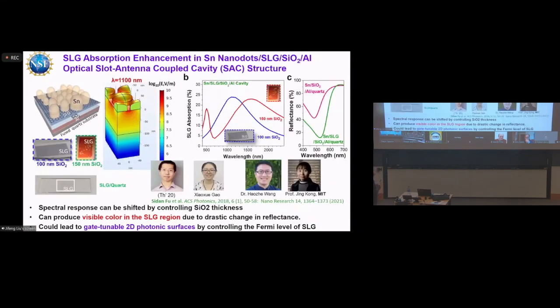So what we did is that we put the graphene essentially on a dielectric cavity, so aluminum mirror on the bottom, dielectric layer, graphene, and then we deposited some self-assembled nano dots with very narrow gaps, around 10 nanometers in between. So essentially, after you do this deposition, you can see a dramatic change optically.